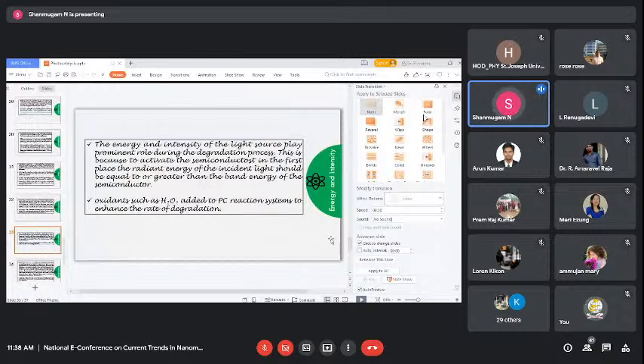Then while fixing the excitation wavelength for photoluminescence, PL, we are asked for the excitation wavelength. If you provide the excitation in the UV region, say 325, you may expect the emission in the visible region. Such emission is possible as a result of recombination of the charge carriers, electrons and holes. So if the PL intensity is very low, we can expect more photocatalytic activity for that sample because the recombination is hindered.